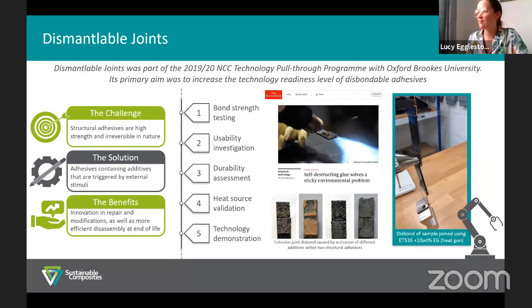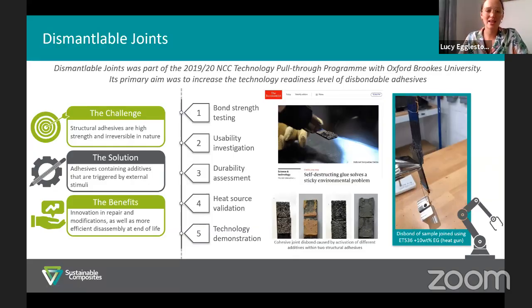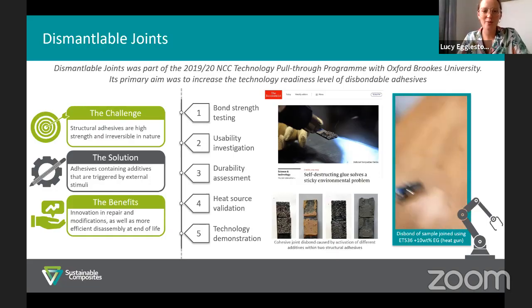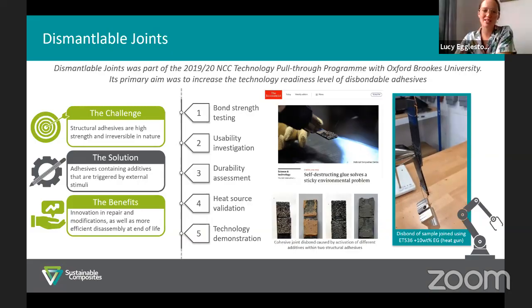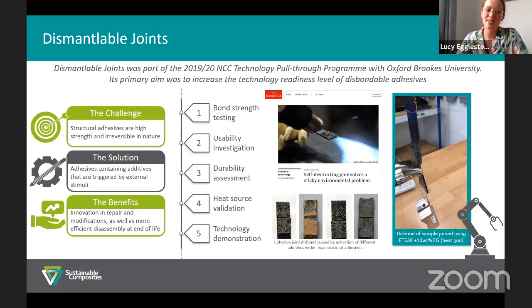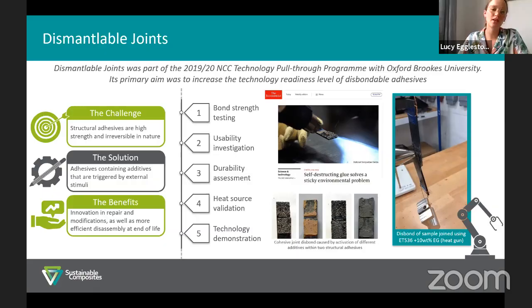There is a video here that hopefully you can see on the right hand side, and that is using a heat gun to activate expandable graphite within a structural adhesive adhered joint. And that happens in the region of about 30 seconds to a minute, but we investigated other heat sources as well that could do it much quicker.